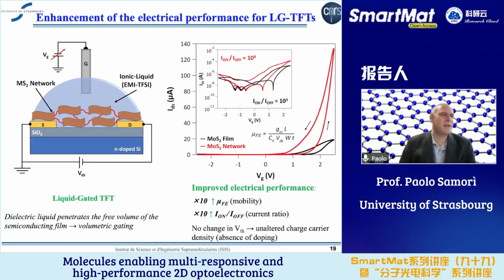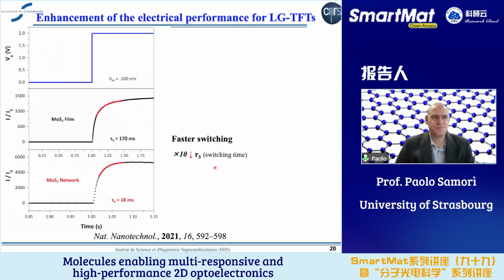Then, of course, we are interested to look at the electrical characteristics of this kind of network, and therefore we exploit a liquid-gated thin film transistor. The reason why we use this instead of a standard back-gated device is because the dielectric liquid penetrates the free volume of the semiconducting film, and therefore we can take advantage of a volumetric gating effect. Without going into the details, comparing the film and the network, we observed for the network a 10-fold increase of the field effect mobility, a 10-fold increase of the on-off ratio, and the threshold voltage did not change, which indicates an absence of doping effect. We also observed that the device switched 10 times faster in the network compared to the film.